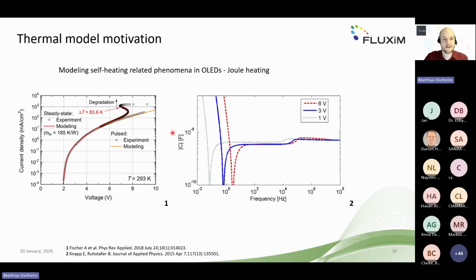So the first important one, specifically for OLEDs, is Joule heating, which is essentially resistive heating. So you drive a current through a resistor with an applied voltage, which leads to heating. And this Joule heating, if you go in OLEDs to larger current densities, you can see here, leads to quite strange effects, because the heating itself then influences the electronic parameters, and you can get quite some peculiar shapes here, which you can model.